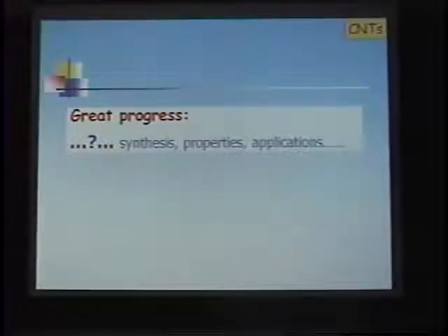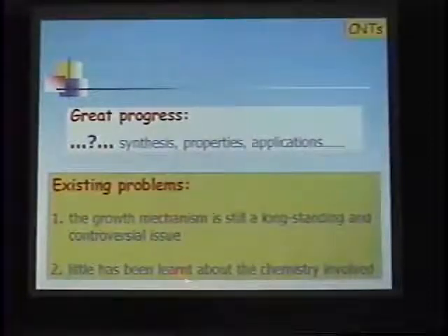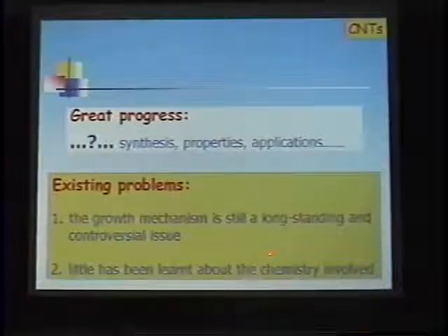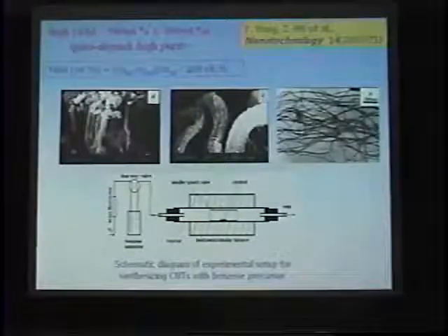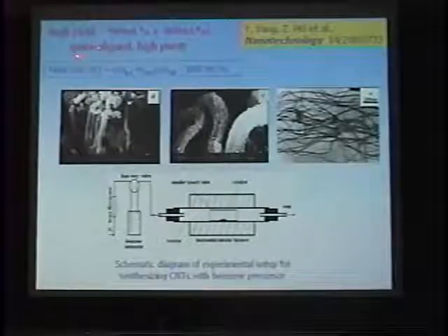As we know, the growth mechanism is a very important issue, since it's not only scientifically interesting but also very useful for possible controllable synthesis of carbon nanotubes. However, today the growth mechanism is still a long-standing and controversial issue, and little has been learned about the chemistry involved. In our synthesis of carbon nanotubes with benzene precursor, we get a rather good quality carbon nanotube, and a very high yield was obtained. The yield is usually larger than 500 weight%. In the literature, it's usually less than 100 weight%.